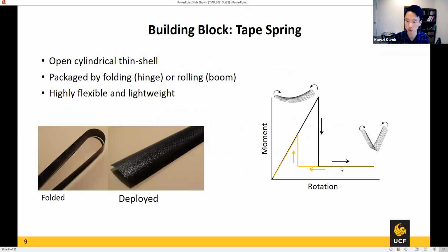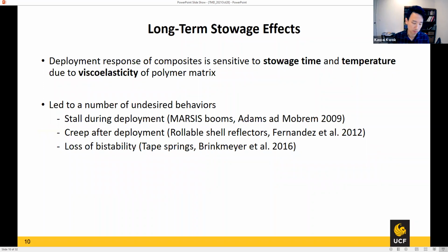So just go back to this real quick, right? On the unloading path, once you release that load, because this is a higher moment, it will obviously go back to a lower energy state. If this is elastic, it will definitely go back, and it wants to go back instantaneously. But if your material is viscoelastic, it does not come back instantaneously. So there's some creep after deployment, and the recovery can take a long time. That is not a good thing for a deployable structure, because we like to have the correct shape, so that we achieve the same stiffness that we designed for, and the same shape accuracy when it's deployed.